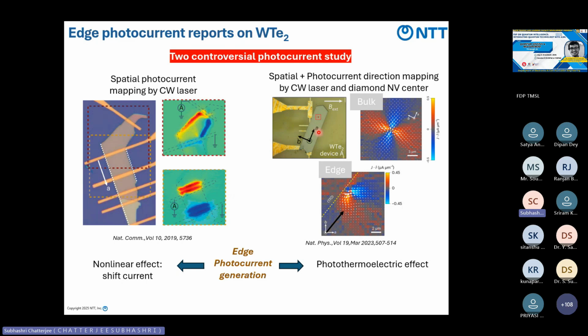But here, they shine the light and say that when you shine light on a material, it generates heat, and the local part becomes very hot. Along the A and B axis a temperature gradient appears, and due to that the electron moves from hot to cold regions, meaning the photocurrent flows opposite to the electron direction.